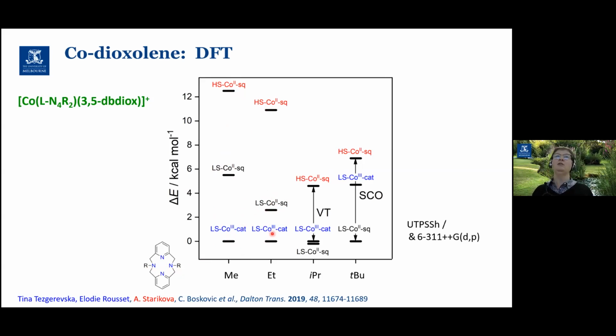So again, those forms, especially that high spin cobalt-2 semiquinone, are too far away for us to access the VT transition at an accessible temperature. On the other hand, when you go to the isopropyl, the calculations actually show that the low spin cobalt-2 semiquinone electromeric form is at the lowest energy, although the low spin cobalt-3 catechol is very close. Experimentally, we find the low spin cobalt-3 catechol form, but now the high spin cobalt-2 semiquinone has come down sufficiently in energy that we can actually access that VT transition, and we see that experimentally.